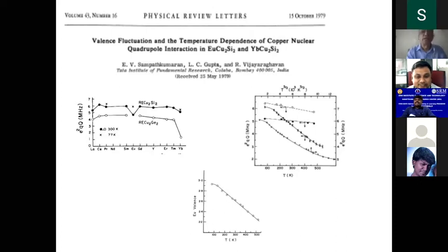Okay. So this is a very beautiful piece of work which we published in PRL, just like that accepted. In those days, even publishing a paper was difficult, and publishing in PRL was much more difficult. This is the electric field. In this case, you look not at the element like europium, which is fluctuating, which is basically a system where, as I already mentioned, an electron goes out and comes back. How do you prove the electron really goes out? The way we have proved is that you look at another element in the lattice and measure the electric field gradient. If the valency changes, the charge state changes, then the electric field also changes.